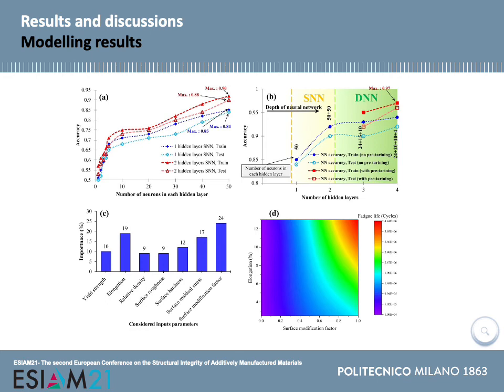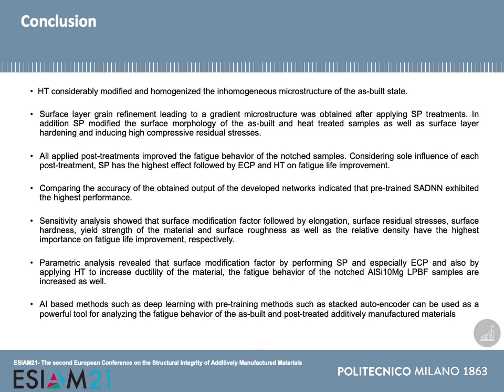And finally, the conclusions. Heat treatment considerably modified and homogenized the inhomogeneous microstructure of the as-built state of the material. Also, we obtained that surface layer grain refinement, leading to a gradient microstructure, was obtained after applying shot peening. In addition, shot peening modified the surface morphology of the as-built and heat-treated samples, as well as hardening the surface layer by increasing the surface hardness and also inducing high compressive stresses compared to both as-built and heat-treated samples.